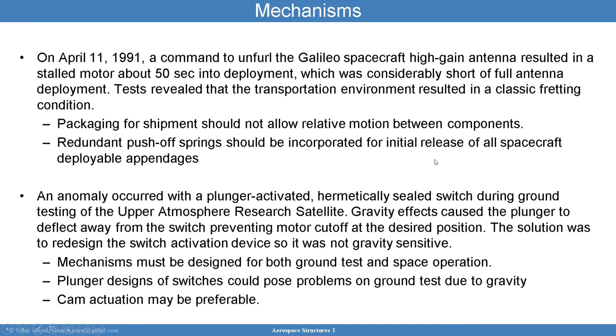On April 11, 1991, there was an issue with a stalled motor about 50 seconds into the deployment. And that was considerably short of the full antenna deployment test. And the test revealed that the transportation environment caused fretting. So you need to make sure that the packaging for the shipment should not allow relative motion between components, and that there's redundancy of the push-off springs so that the initial release of the spacecraft deployable appendages could occur.